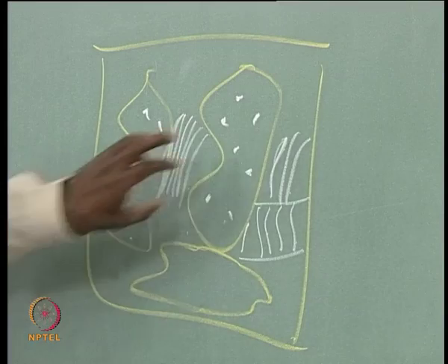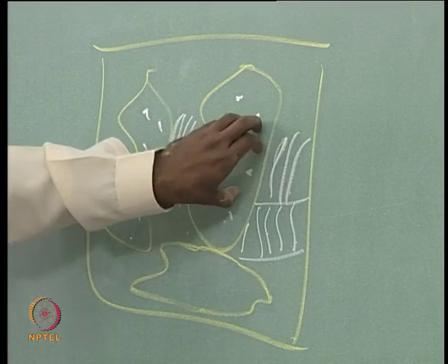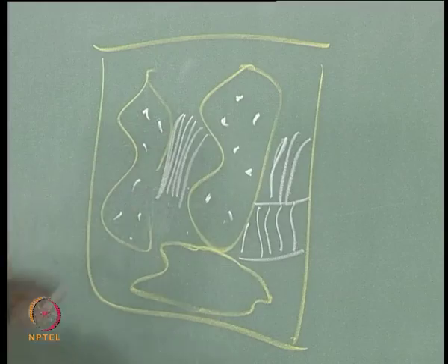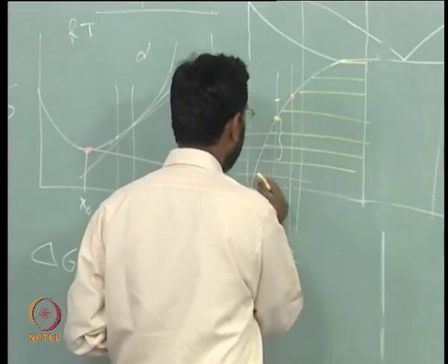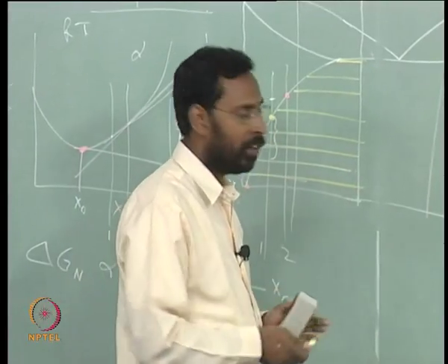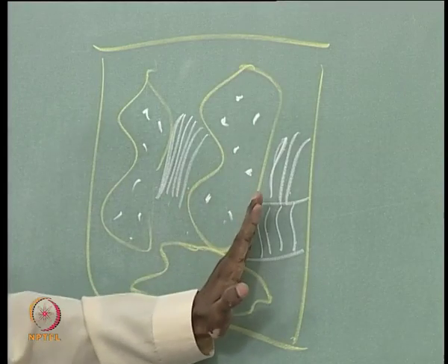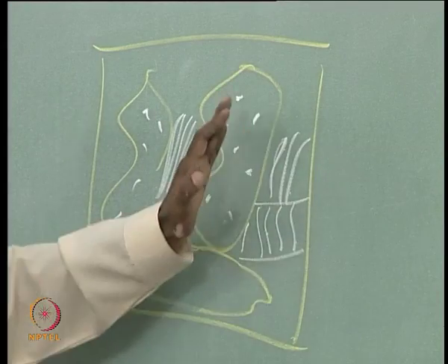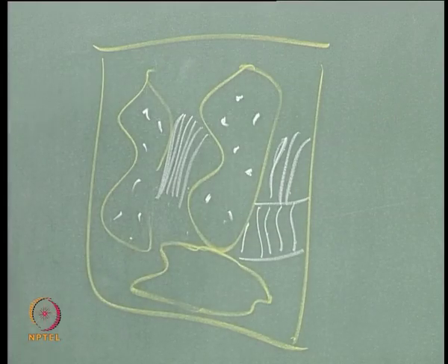Because again, this copper which is there inside the dendrites, we are doing age hardening at this temperature, let us say. So if it has to nucleate on the theta which is there, it has to travel a larger distance, and these grain sizes are generally 100 microns or so.